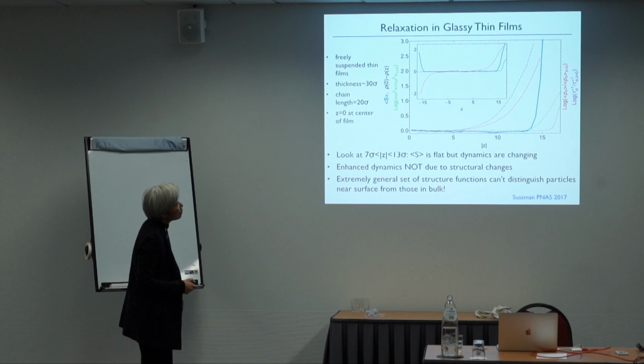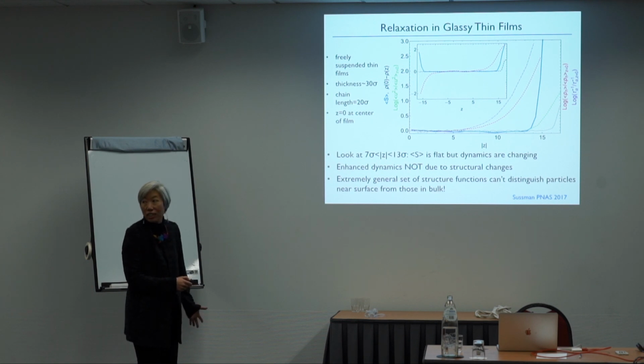Okay, so we looked at thin films, and this is 1 over the relaxation time, the purple or the red. It doesn't matter, I have 2 different measures of it. This is the center of the film, and this is going to the edge of the film. The black line here is the density difference between the center and the edge of the film. The density difference is 0, of course, at the center of the film, but as I go to the edge of the film, it changes. The edge of the film has a lower density. So this is the density at the center minus the density at where I am. This is where the density falls off, so that's where the surface of the film is. This tells you where the edge of the film is.